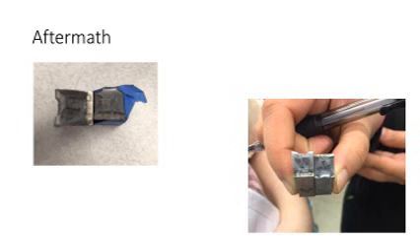Here are two samples after the Charpy impact test. The faces of the fracture can be examined to compare with the basic images shown earlier. The left sample is a 1080 steel sample at room temperature. The right sample is a 1080 steel sample bathed in ice water before impact. Both show some plastic deformation, but the room temperature sample shows more.